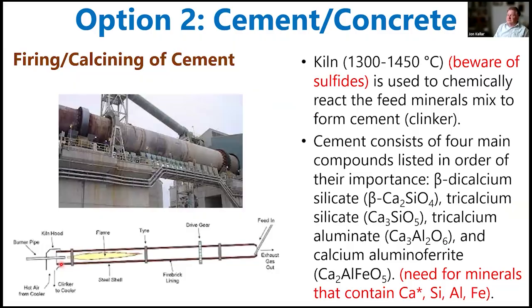And so in terms of cement production, I'm showing a kiln on the left, and that it's fired at a temperature somewhere between 1300 to 1450 Celsius. I say beware of sulfides, right? If you have sulfides present, they're going to go out the stack as SO2. So probably tailings that contain sulfide minerals would not be a wise choice.